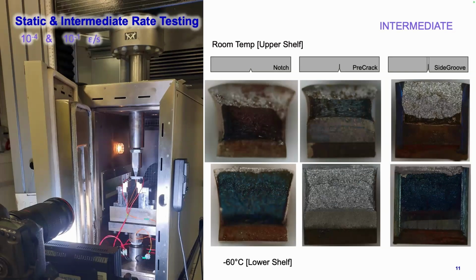So the same for the intermediate speed, so a bit faster than what is classified as static. It's definitely a brittle material. It's snapping through. This is the intermediate test for a pre-crack sample. So this is as it ran in live time scale, not sped up. It's pulling apart, and I can see, even just with the naked eye, plastic deformation. So it's certainly not breaking in a brittle mode. This is in the lower shelf, so this is minus 60 degrees Celsius. So it's still showing a ductile mode, even though my force histories and the energy curve would expect it to be brittle.